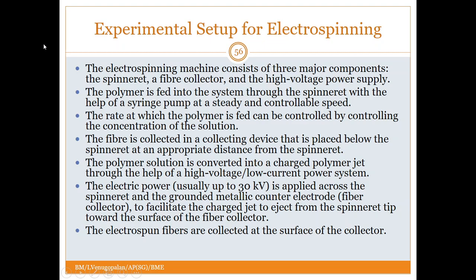The electrical power for the system is usually up to 30 kilovolts, and this is applied across the spinneret and the grounded metallic counter electrode, which is the fiber collector, to facilitate the charged jet to eject from the spinneret tip towards the surface of the fiber collector. So you basically apply charge across the spinneret and the collector, which would attract the polymer fiber from the spinneret towards the collector. It's just like how electrons get attracted towards positive energy. Electrospun fibers are collected on the surface of the collector.